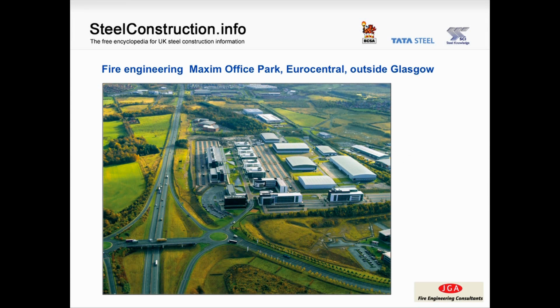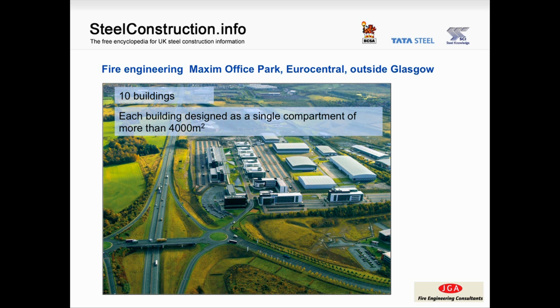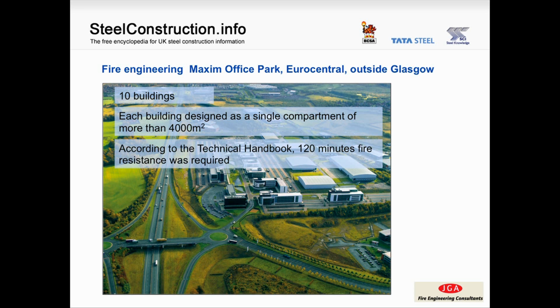A more recent example is Maxim Office Park, which we can see here. This is Eurocentral outside Glasgow, where time equivalent calculations enabled the engineer to demonstrate that a general reduction in fire resistance periods from 120 to 60 minutes could be justified. In total, there were 10 buildings, and from Scotland's Technical Handbook 2, because each building was a single compartment of more than 4,000 square metres, the fire resistance requirement was 120 minutes.